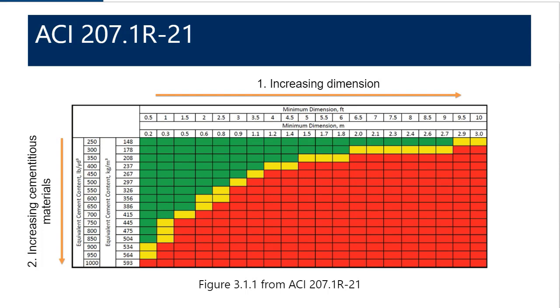And so we've seen some instances in mass elements where the contractor actually complied with the 35 temperature difference specification, and they did still end up with some thermal cracks. And so again, the thermal cracking is a function of time and temperature. And so if the concrete doesn't have enough strength at a given moment in time to resist those early age tensile stresses, it can crack.